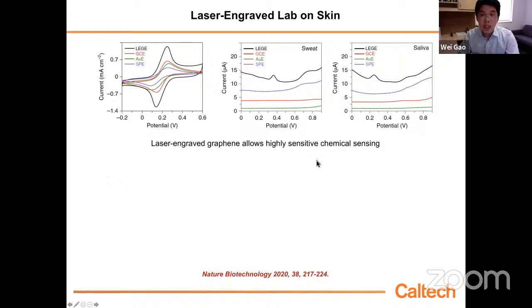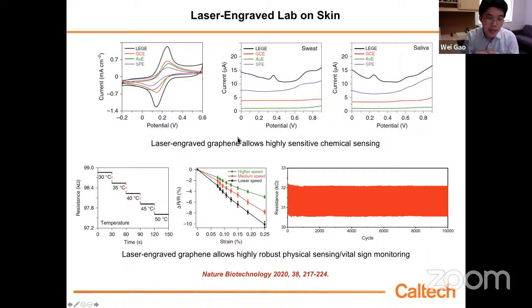This laser engraved graphene electrode has very good performance compared to the classic glassy carbon electrode, gold electrode, or screen printed electrode. You see the CV, and if we do the DPV scan from sweat and saliva, we can see significant peaks for uric acid and tyrosine compared to other electrodes. Other electrodes don't see clear peaks, but here it's very clear. That means it has very good performance for detecting electroactive molecules. The physical sensor designed with the laser engraved graphene has pretty good performance as well.